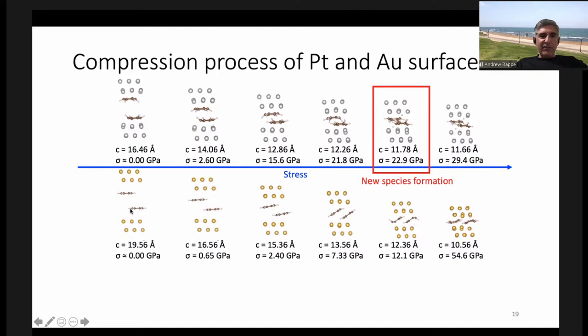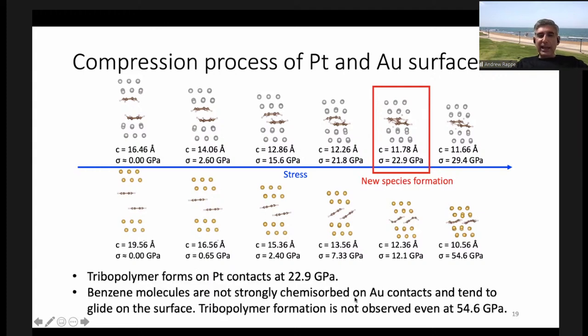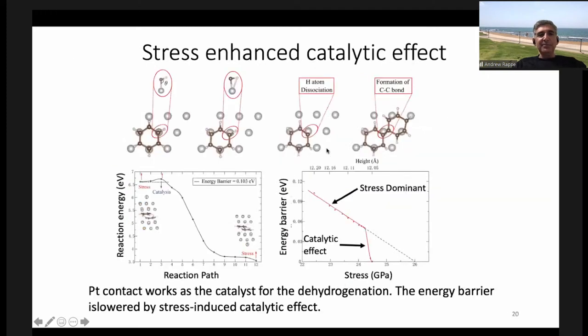Gold is actually very interesting also. It starts to compress and the molecules tilt and they tilt more and more and they slide away. And even at 50 GPa, they don't react. And so we were pretty excited about that. But it turns out that gold is totally impractical for nano electromechanical devices. It's too soft. And you know this if you've ever had gold jewelry. It can't take the pounding of the tapping of that cantilever. So yes, gold is unreactive, but that also makes it too weak to use.